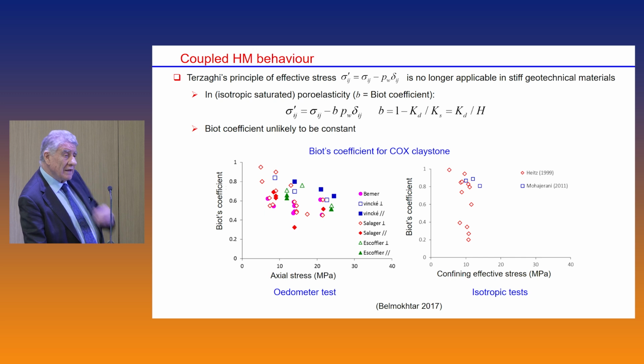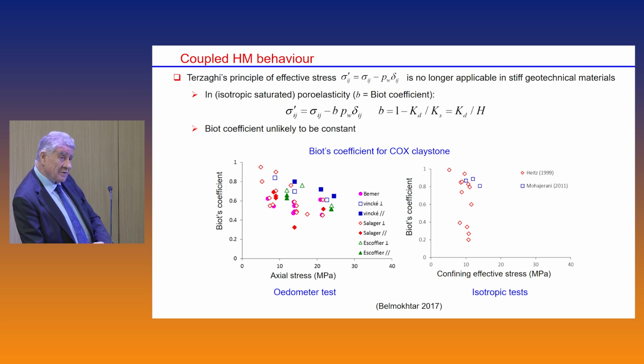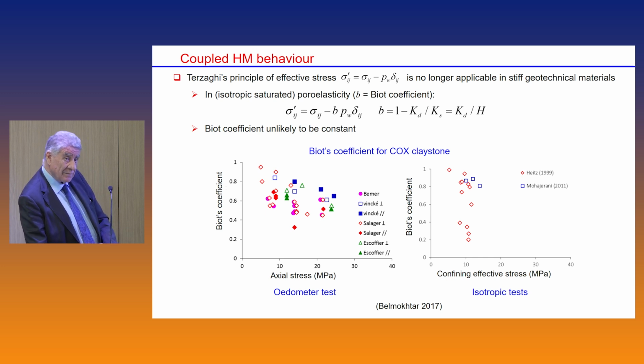The hydromechanical coupling in soils is very easy. It is defined by Terzaghi's principle of effective stress, but things are not so easy when the materials become stiff, like in these stiff claystones that we have already mentioned and we'll see later on. If we stick to poroelasticity, this coupling can be defined by the Biot coefficient, which may be isotropic or anisotropic, and obviously, since it controls effective stresses, it is an important parameter, and there have been plenty of measurements trying to identify this parameter, with a very big scatter, some values which are not really credible.